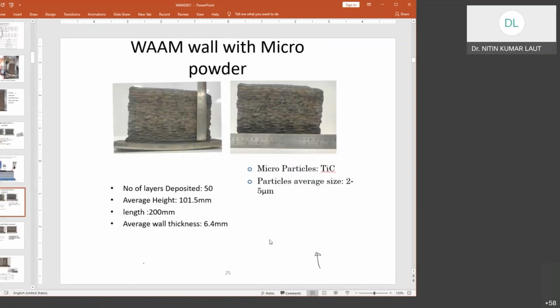Then there is a comparison between two specimens, where in one specimen we have used powder, and in the other specimen we have just used wire. The other is wire plus powder. So you'll find some typical difference in that. We have already discussed the one without powder, but in this specimen, you'll find better layer deposition if you are using microparticles of titanium carbide. Other performance aspects we'll discuss in subsequent slides. The particle size they used was 2 to 5 micron. We have compared the additive manufactured product with and without powder, but specifically we have used micro powders.